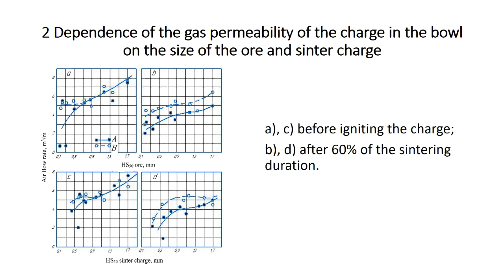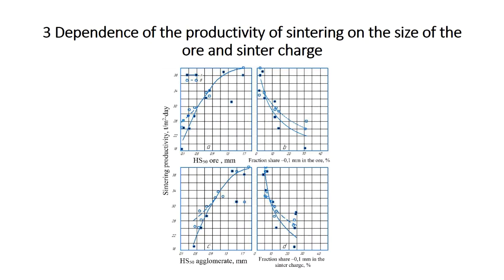Figure 3 shows the dependence of the sintering performance on the size of the ore and sinter charge. In the same way as for gas permeability, differences between the two ores were found for the sintering performance in the area of fine fractions, Figure 3, a and b. These differences are found when the value of the Hs50 index for ores starts from 0.6 mm and for the entire charge starts from 1.0 mm, which coincides with the corresponding data for gas permeability.